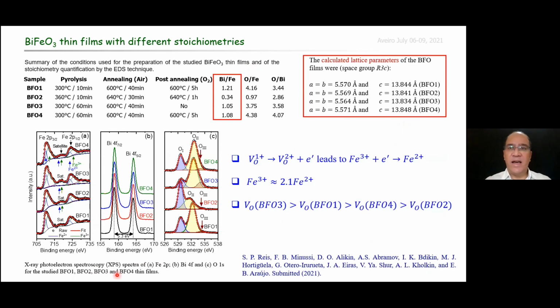Based on the XPS analysis summarized in this figure, we observed the presence of both iron 3+ and iron 2+ for all studied films, as indicated in figure A. In figure C, we observed oxygen vacancies with different oxidation states for all films. The oxygen vacancy concentration is higher in the BFO3 film and smaller in the bismuth-deficient BFO2 film. This data will be important for the next discussions.